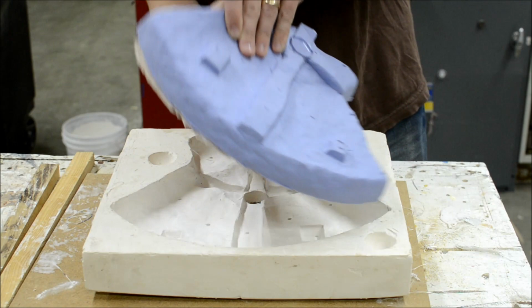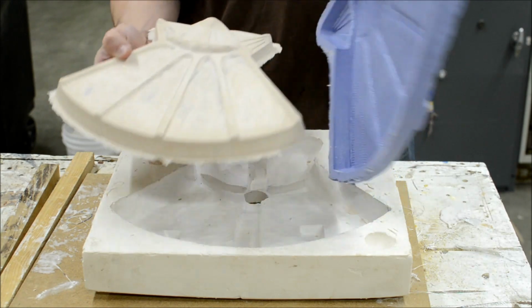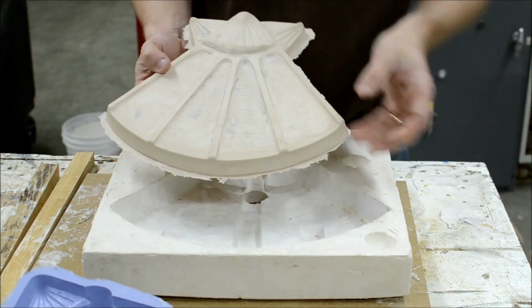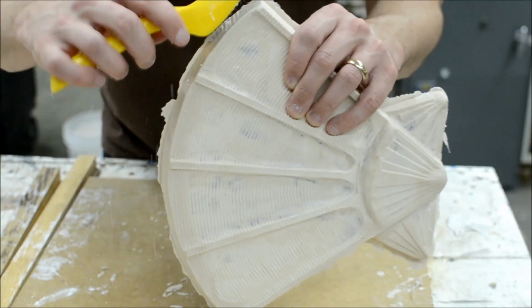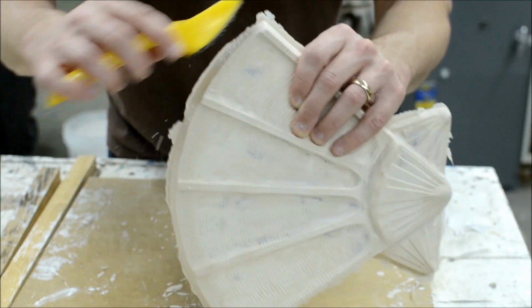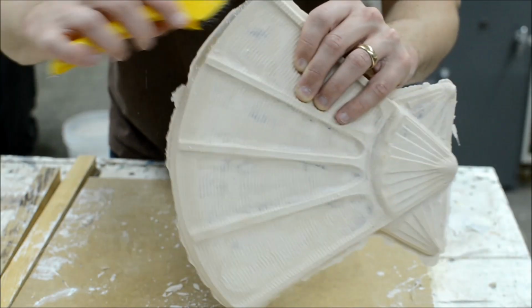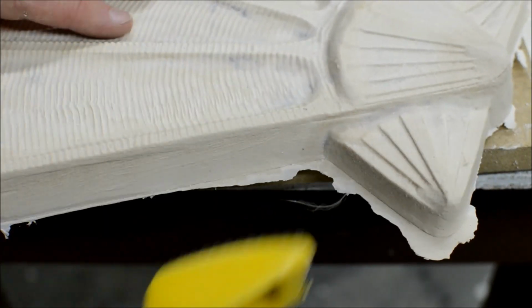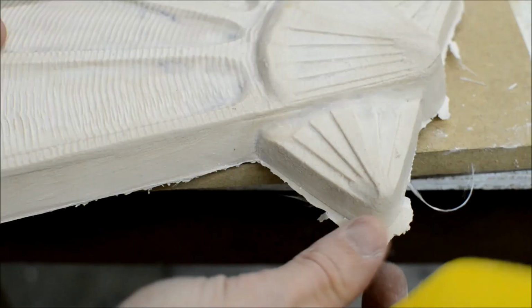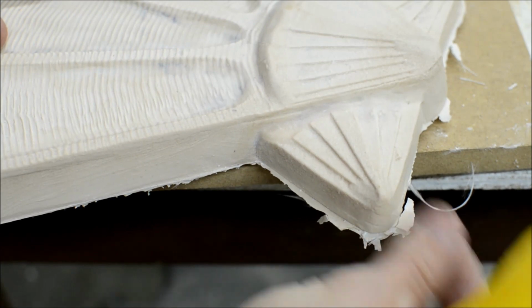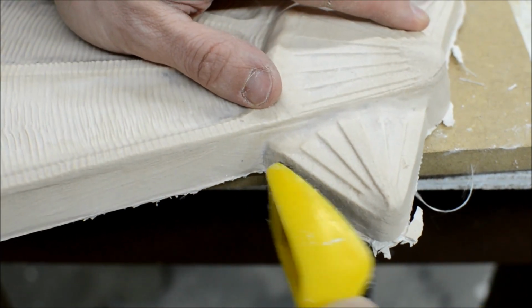Aqua Resin has a beta stage, which lasts about 24 hours, where the resin is dry and solid, but not yet rock hard. Any rasping, filing, or sanding is best done during this phase. Sanding releases tiny glass particles and fibers into the air that are highly irritating, so wear a mask.